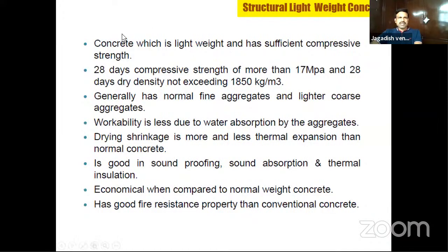There is also what we call structural lightweight concrete. So here, the condition is you should have a minimum of 17 MPa strength, and the dry density should not exceed 1850 kg per cubic meter.